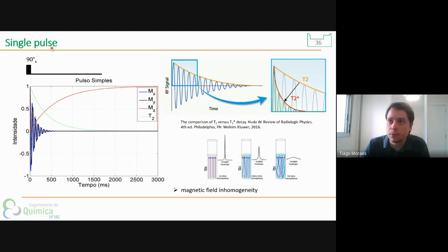Here again, the single pulse, just one pulse, in low field, as I said, the magnetic field is not so homogeneous. It is an inhomogeneous field. So this will affect the signal more. So here we also need to show you the T2 star, that is the time that the magnetization will disappear, faster than the T2 time that was what you expected. So this comes from the inhomogeneity of the magnetic field, right? So if we want to obtain the real T2 value, we need to use some special pulse sequences.